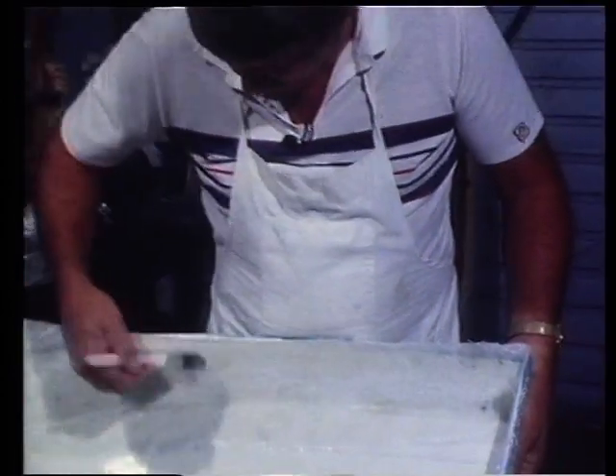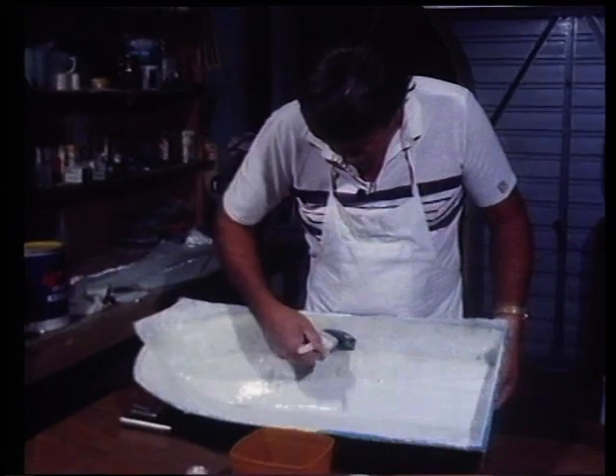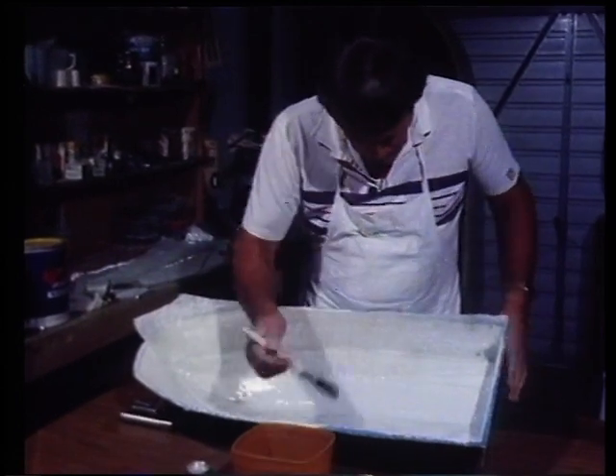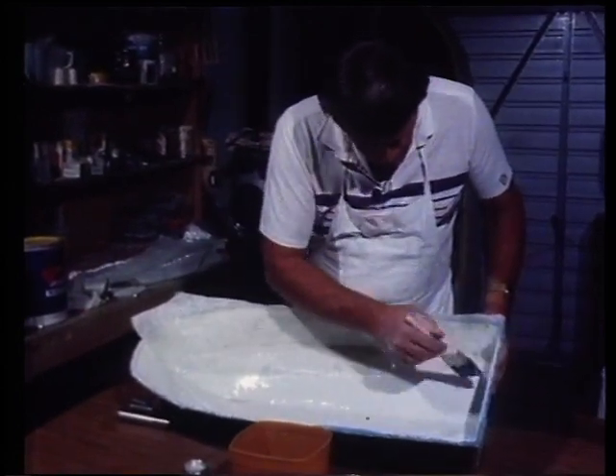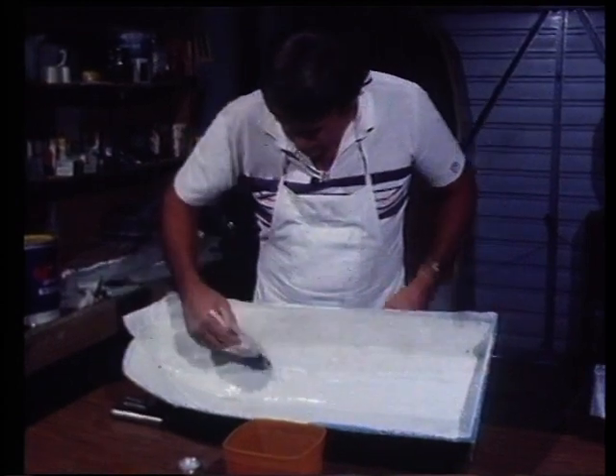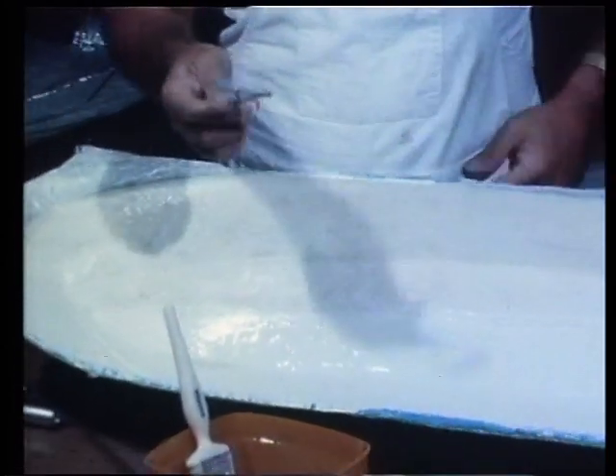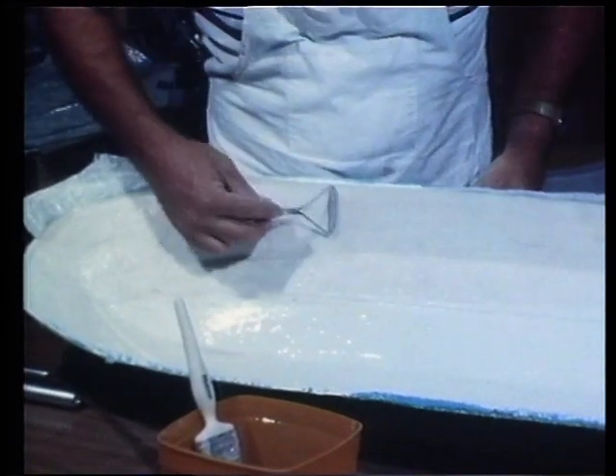Now, that glass is held in its mat form by a binder which is soluble in the resin, so all of those strands have been sprayed onto a continuous table, and they've been sprayed with this binder, which dissolves pretty well on contact with the resin. So after I've stippled the resin into the glass and it's lost its clear look, I'm pretty well certain that the binder has dissolved. It is then time for the next and most important step.